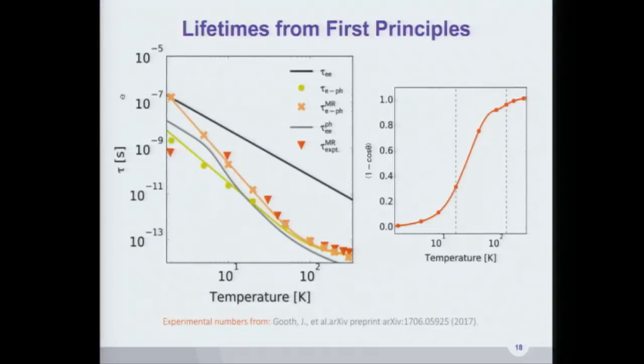Okay, so we said, let's look at the microscopic picture. Let's look at the lifetime contributions from the different processes and try and recover this hydrodynamic regime. Something we can do in our calculations is look at not only the traditional electron-electron scattering, but also electron-electron scattering that is mediated by a virtual phonon. And we wanted to say, OK, so if we calculate a handful of different types of lifetimes and look at them as a function of temperature, again, we explicitly calculate them as a function of temperature, we should at some point see one particular lifetime that is really, really long or somehow starts to dominate the physics. And that would be indicative of us recovering that hydrodynamic regime.